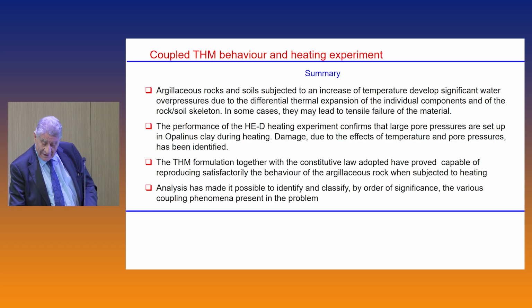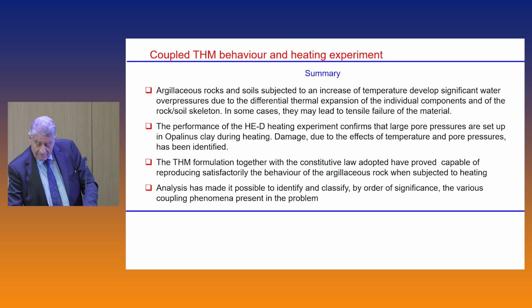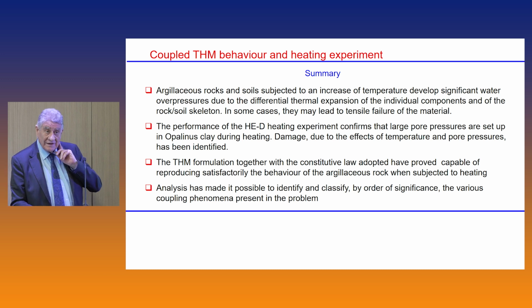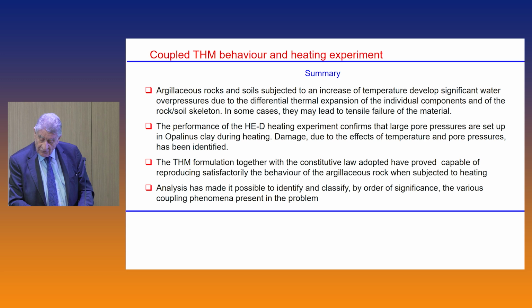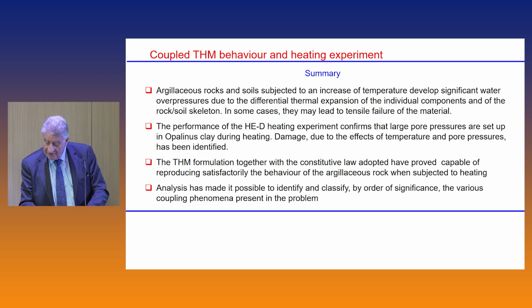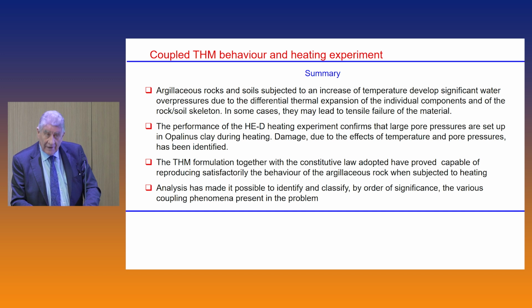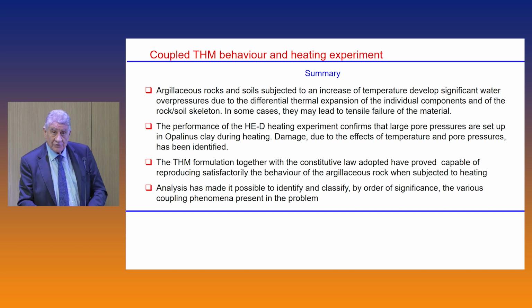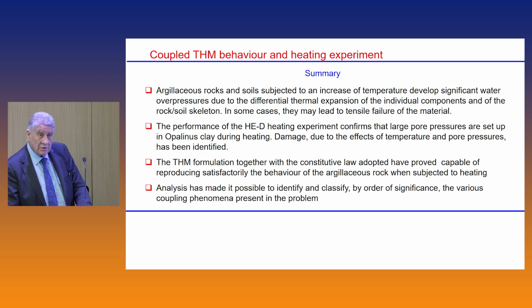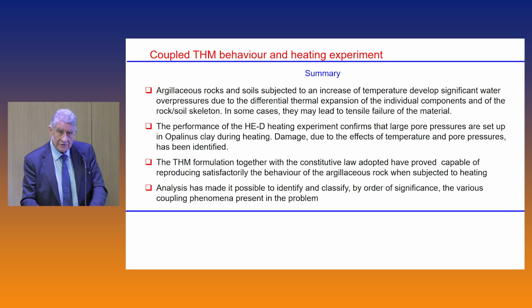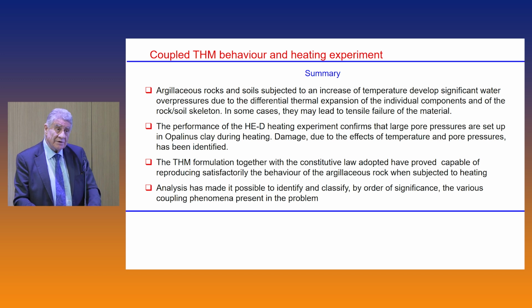Okay, so let me summarize this last part. Argillaceous rock and soil subject to an increase of temperature develop significant water pressures, mainly due to this differential thermal expansion, and this may have practical consequences. The performance of that HE-D test in Mont Terri, the one I was describing in some detail, confirms that large pore pressures do actually materialize, and they may cause damage. And the coupled formulation together with the constitutive model seem to be able to capture reasonably well the main features that are observed in the field. As a consequence, we can get a better understanding by classifying, for instance, the different degrees of coupling within the different components of the problem.